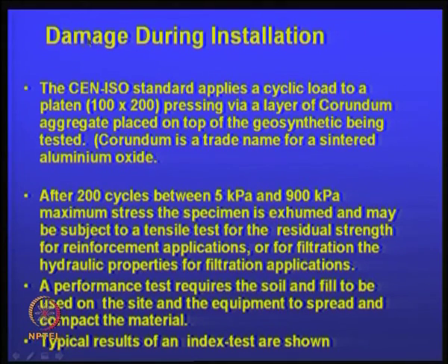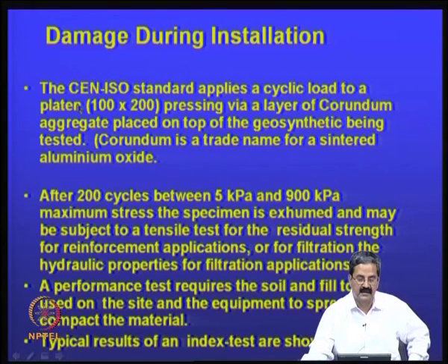And there is another test, if you want to understand what damage can occur during installation. Again, this is a European standard in which you have cyclic loads applied, 200 cycles between 5 to 900 kPa, and the maximum stress is assumed. After the maximum stress, the specimen is removed, and again you test it for a tensile test or a filtration test.